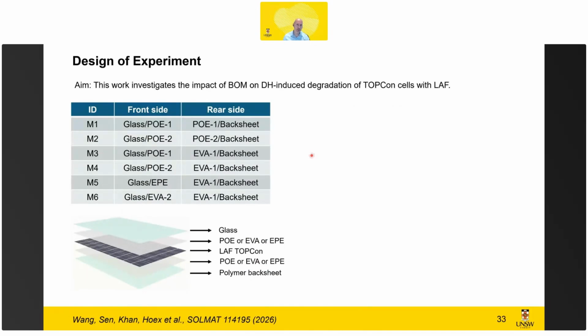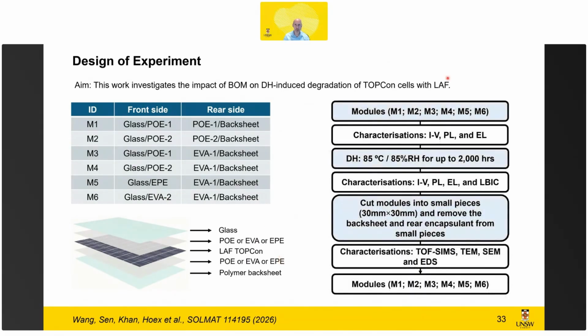So we prepared several mini modules again. So 6 types of mini modules with various types of POE and EVAs and EPE, which is a mixture of EVA and POE. So it also contains EVA. So you would potentially put an acid scavenger in there. And then we again did just normal damp heat testing, 2,000 hours, because it's modules. And then we looked at very detailed characterization.